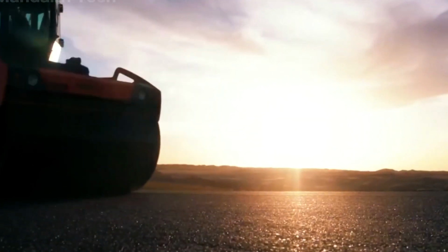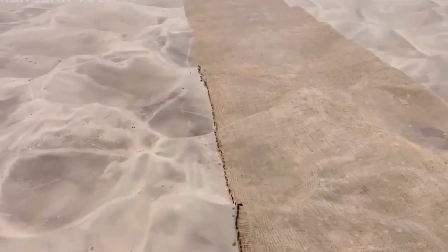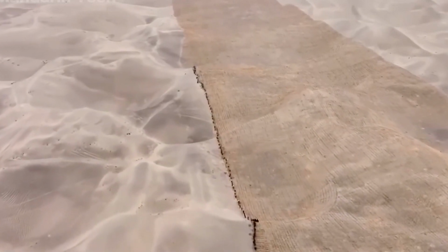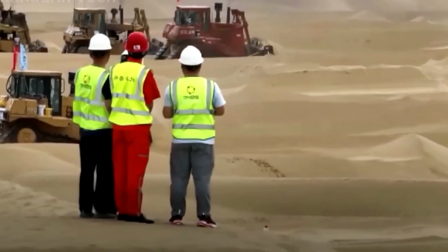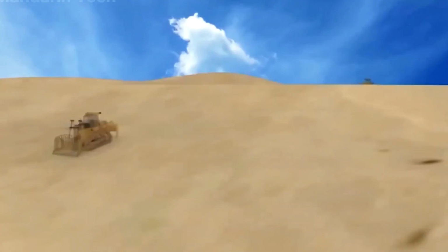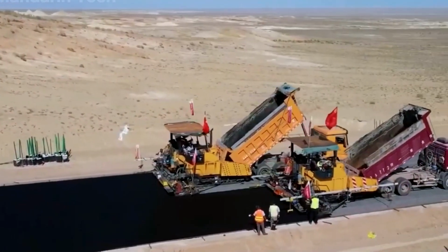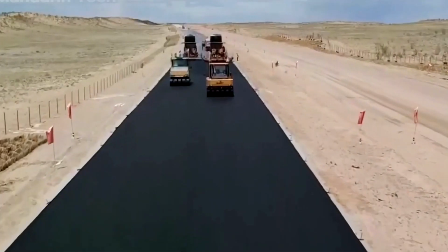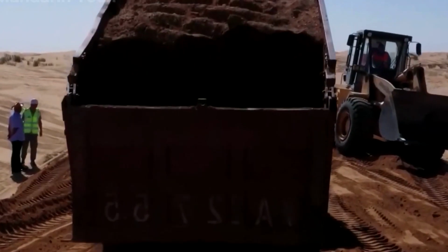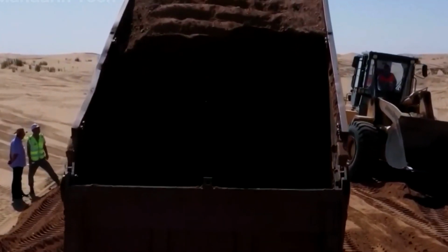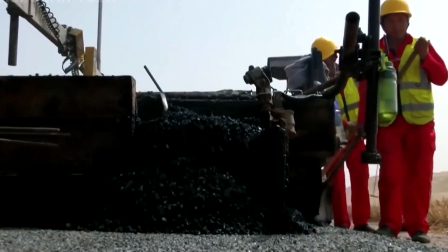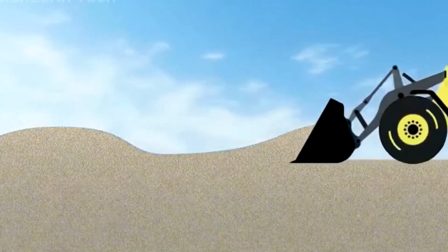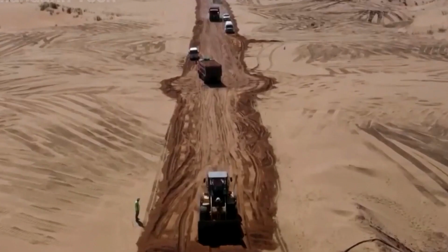Portable asphalt plants roar to life at the edge of the desert, heating stone, sand, and polymer-modified bitumen to nearly 170 degrees Celsius. Insulated tankers deliver this hot mix non-stop to the paving machines waiting on site. One can notice the glowing asphalt being spread in layers about 6 centimeters thick. Steel rollers follow close behind, compacting the material before it can cool. This process repeats in a tight choreography, with the paver, roller, and finisher moving forward like a synchronized machine.